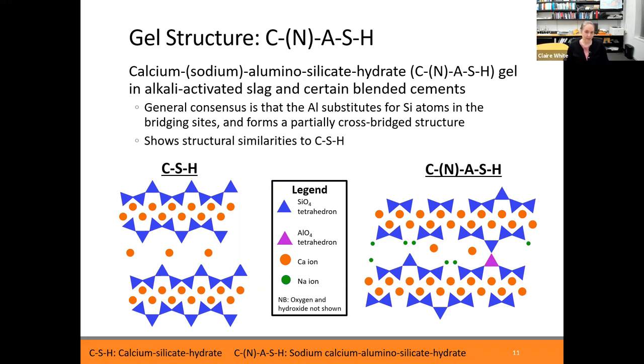Okay, so on the left on this slide is a representation of the calcium silicate hydrate gel without showing oxygen atoms, without showing hydrogen atoms, but just showing the calcium ions and these silicate chains. What's known is it has this layered structure at the nanoscale. These chains are of finite length that can be quantified using nuclear magnetic resonance. And then there's these calcium oxide layers, and these calciums are actually interlayer calciums, and they're solvated by water molecules. So this is CSH, and the structure of CSH is quite well known. If we add sodium and aluminium into these systems, we know some things.